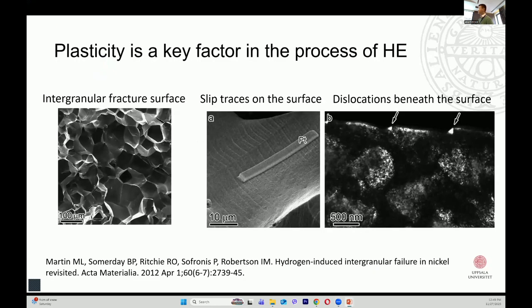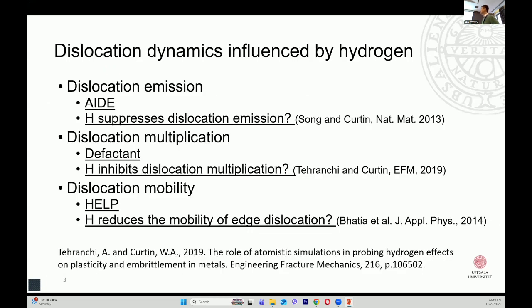Since this session is dedicated to hydrogen embrittlement, I believe there's no need to reiterate the basics. But I think what we need to keep in mind is hydrogen embrittlement is featured by a global reduction in ductility as well as a local transition from ductile to brittle fracture. And there has been sufficient experimental evidence showing the existence of plasticity under the seemingly brittle fracture introduced by hydrogen. And this highlights the important role of dislocations or localized plasticity in hydrogen embrittlement.